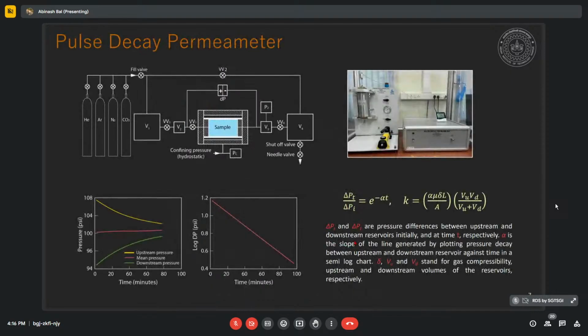So to study experimentally the flow behavior in a shale matrix, we used 1-inch diameter core plugs and a pulse decay permeameter instrument. This is an in-house facility in the experimental rock deformation laboratory, an unsteady state permeameter in which we put the sample here. This is the sample chamber. We put the sample here, we apply the desired confining pressure.